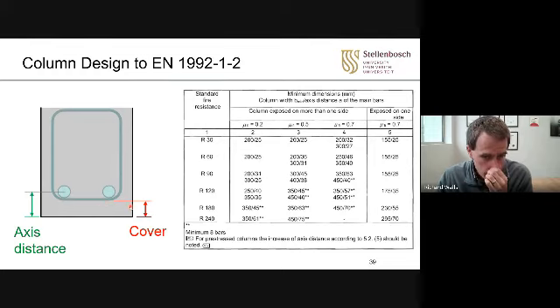And what you normally do, the cover is 25 or 30 mm, but the cover is actually of secondary importance to what's called your axis distance, because the fire is applied on the outside, the heat penetrates through the concrete, and more or less where it gets to the middle of this reinforcing steel, this rebar, that's what you're worried about. So if you use the axis distance rather than the cover, you can sometimes develop more efficient systems. So in the Eurocode, it has axis distance.